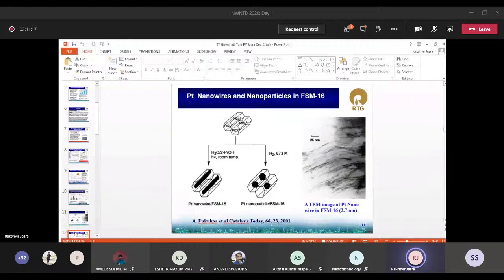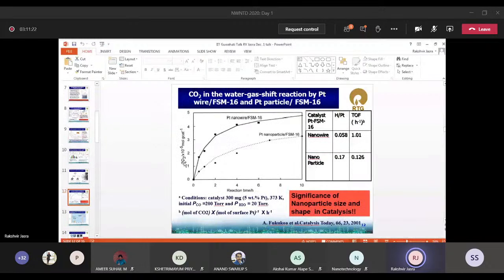Now important is when you have got platinum nanowire inside the FSM16, the activity is an order of magnitude higher compared to spherical nanoparticles, under similar conditions, for carbon dioxide formation in the water gas shift reaction. So this is also very, very important information, because this tells you nanoparticle size is important in determining the catalytic activity, but the shape is also very important. Now different